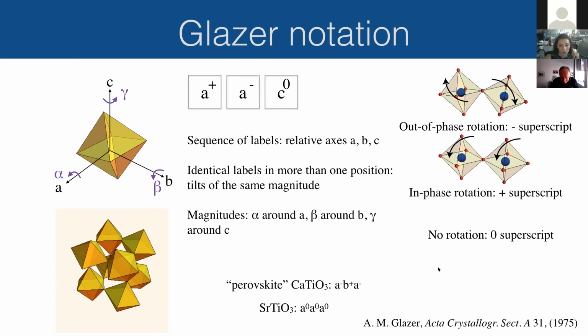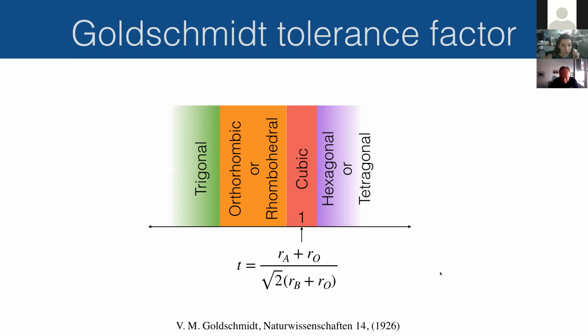So another way of describing distortions in the perovskites is through the Goldschmidt tolerance factor. This is an empirical relationship between the sizes of the ionic radii. This is the tolerance factor T, and it depends upon the ionic radius of the A site cation, the B site cation and the oxygen anion. When you calculate this, it's just a geometric ratio. If you get 1, chances are that structure will be cubic. It's not perfect every time, but it's usually got quite good predictive power.